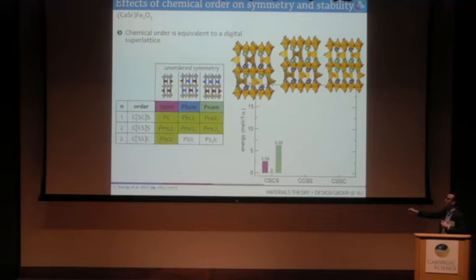The ones that have polarization in the layering direction, it seems like to switch them, you need to shift the A sites. You have to shift the oxygens. You have a deficient layer and a non-deficient layer, and you have to shift the oxygens from the non-deficient layer to the deficient layer in order to switch the polarization in that case, right? Right, which is why I focused on this one, because the component of the polarization we wanted to switch was the one that's not along the long axis. Okay, now I understand. Yeah, I didn't make that clear, but you're right. But if you don't have to switch the polarization, you just want a broken inversion symmetry crystal, you're fine.